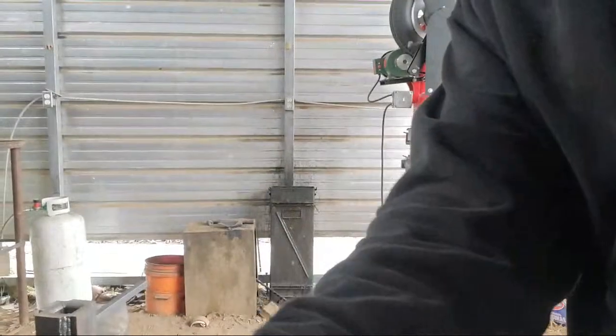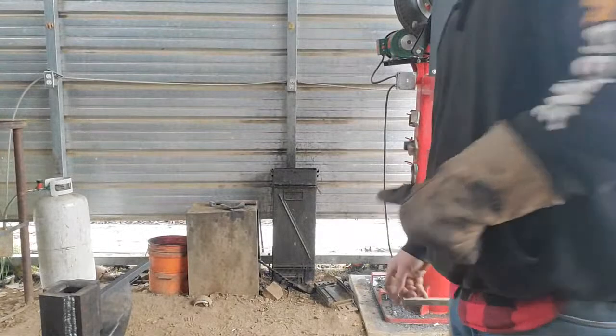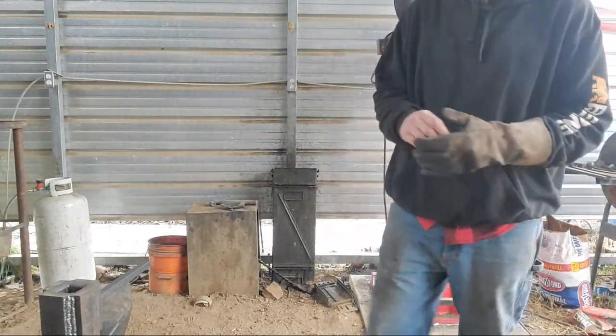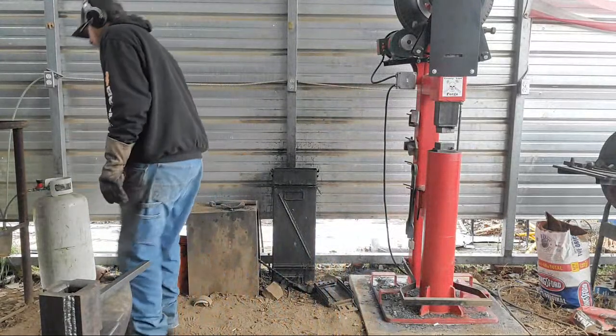So at a low heat, it'll start scaling faster than mild steel or high carbon steel because it has that chromoly, manganese, whatever. All those different compounds in there that when they get hot, they off-gas and create their own type of oxidation at a low temperature. So that's why you got to flux that shit fast and early off your forge weld, or it'll be really tough to stick it to itself. It ain't got nothing to do with the carbon. It's all about the chromium, the way that shit works. Chromoly.